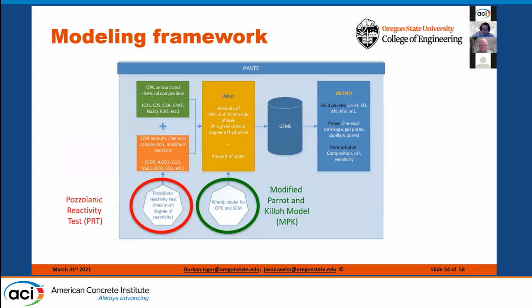Now, how does all of this get put together? And I think this is really where this whole thing starts to come together and tell a really nice and interesting story. So we can take the original amount of the OPC and the chemical composition of the system, right? And we can put that together with our SCMs in the system. So we need to know things like the chemistry. We need to know things like the kinetics, but we also need to know how much of the material is going to actually react. And for this, we determine this from a pozzolanic reactivity test, which is similar in nature to the R3 test, but it's actually designed specifically to tell us about the pozzolanic reaction. All we want to know out of that test is the pozzolanic reaction. So we put calcium hydroxide, pore solution, and whatever material we're after into a system, and we figure out how much of that system is going to react. And we use that as an input into this model.